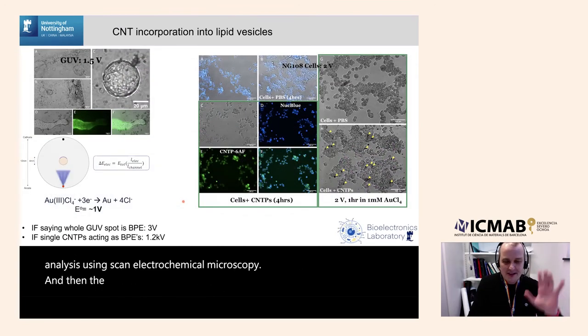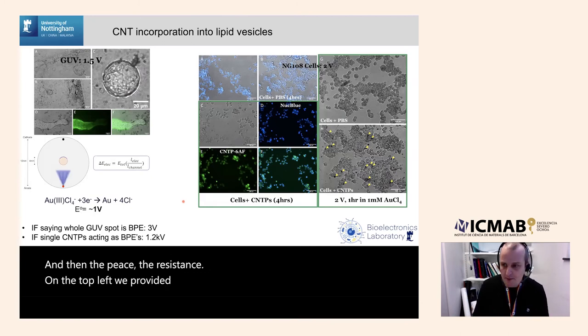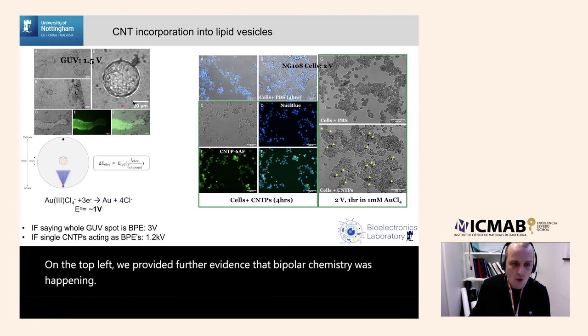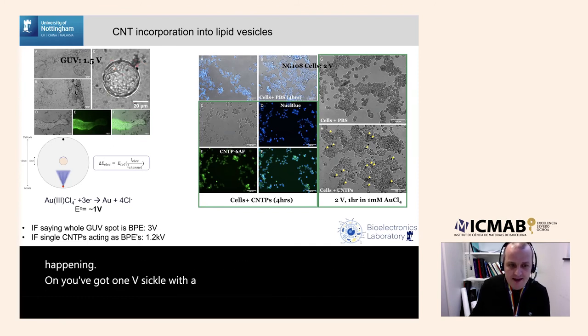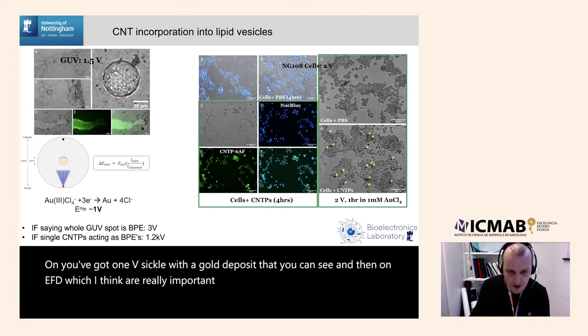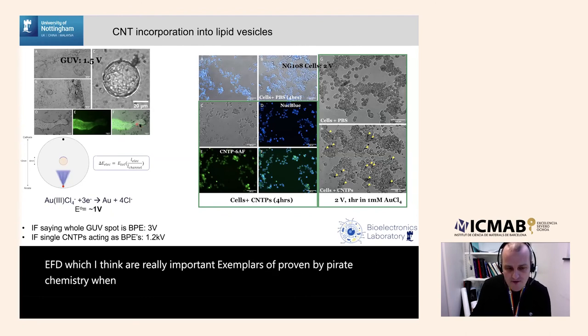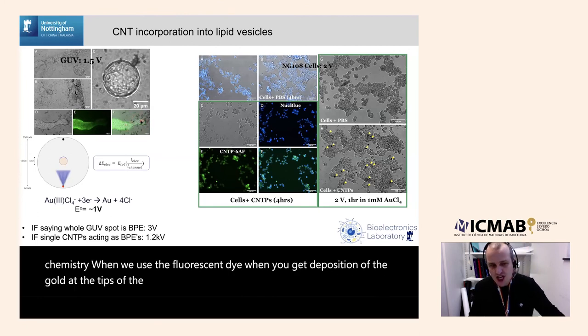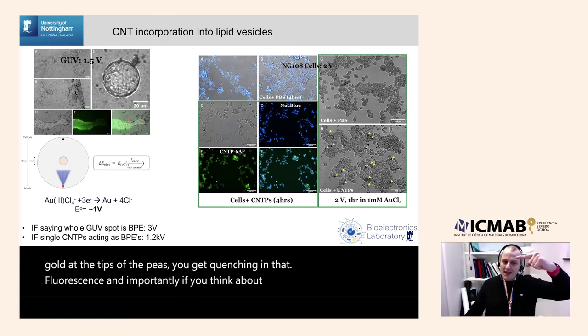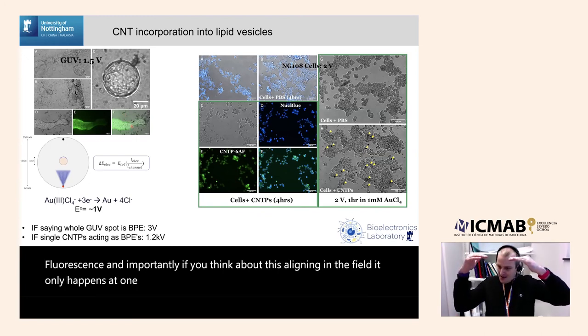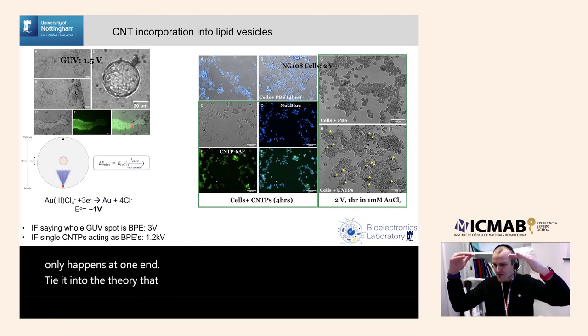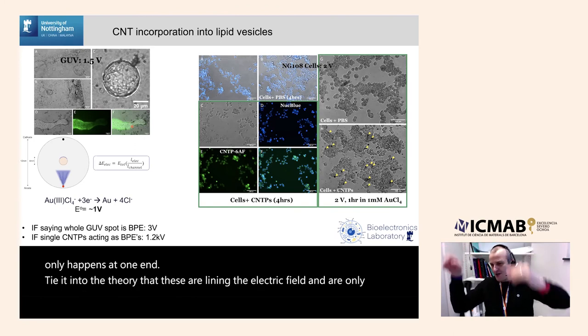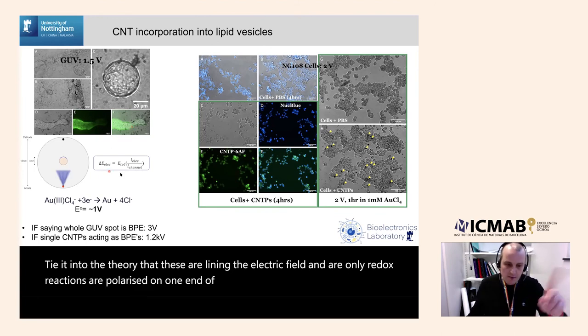And then the piece de resistance, on the top left, we provided further evidence that bipolar electrochemistry was happening. On C, you've got one vesicle with a gold deposit that you can see. And then on E and F and D, which I think are really important exemplars of proving bipolar electrochemistry, when we use the fluorescein dye, when you get deposition of the gold at the tips of the CNTPs, you get quenching in that fluorescence. And importantly, if you think about this aligning in the field, it only happens at one end, tying into the theory that these align in the electric field and redox reactions are polarized on one end of the vesicle.